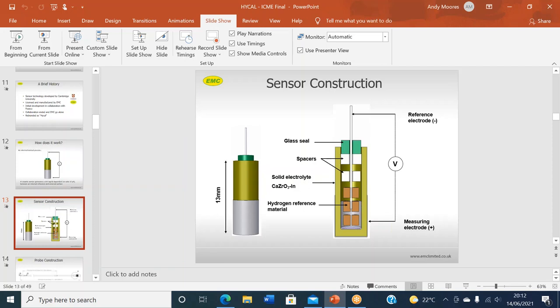Yeah. It wouldn't necessarily be the precise hydrogen level in the ingots that you receive from the remelter. No. Would you expect it to be lower though, if you've sent it off to a secondary smelter? They're not obviously sending this exactly the same material back, are they? But it would depend if the secondary smelter did any degassing treatment. If the secondary smelter simply melted it and cast into ingots, I would expect it to be a relatively high level. If the smelter has a degassing unit and treats the metal before casting into ingots, then it will be lower, probably. Yeah.